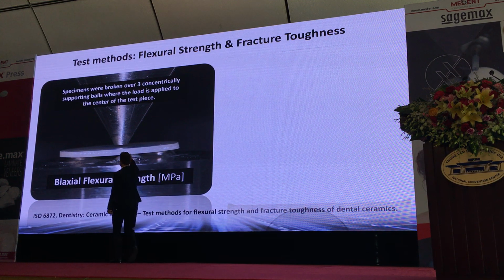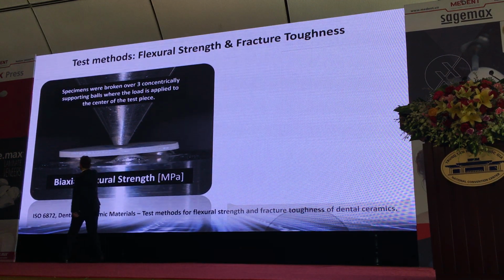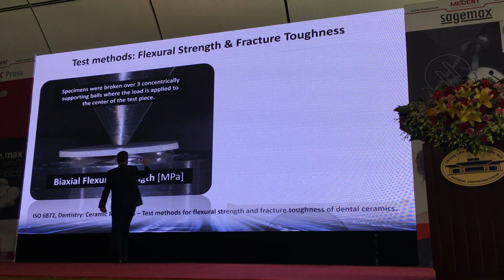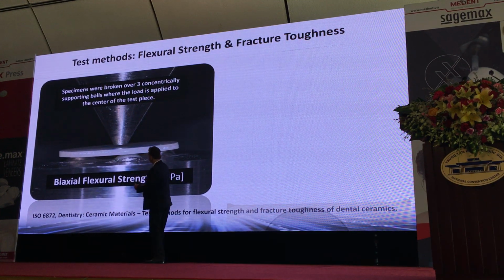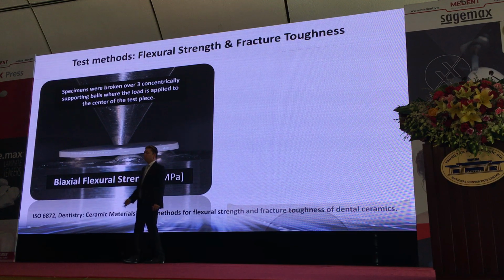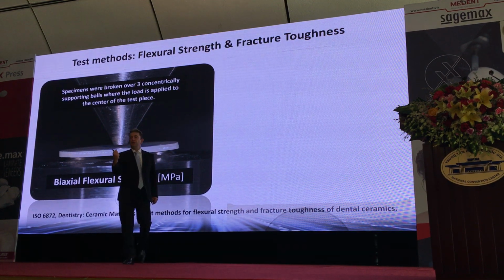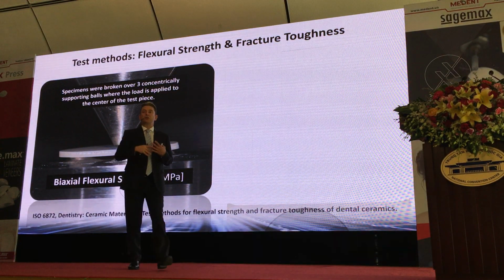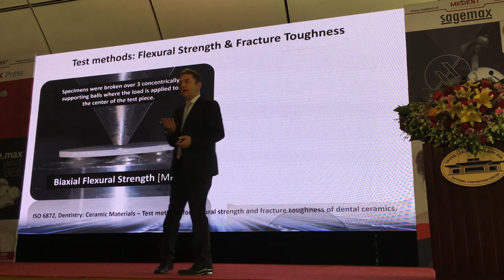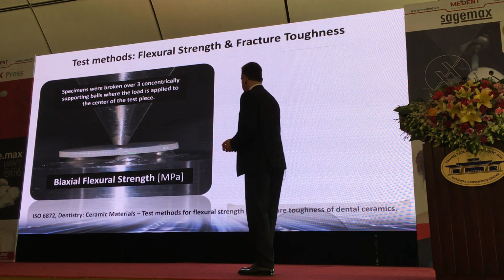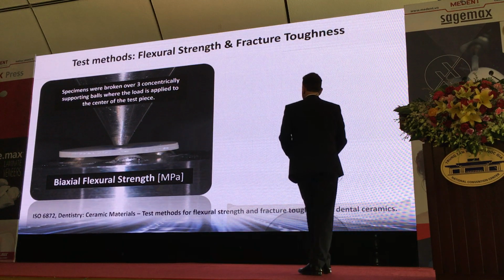So you have a sample of ceramic, and then this is loaded on 3 different points. Then it's loaded from the top until it fractures. And the force that we need to fracture it is calculated by the area, by this area here. And this is calculated in megapascals.